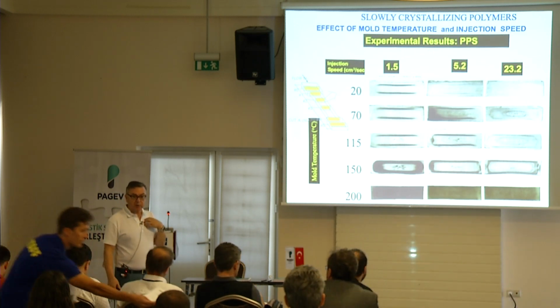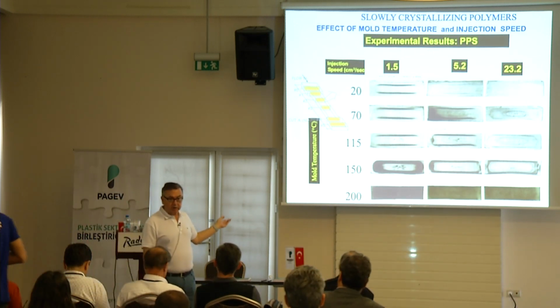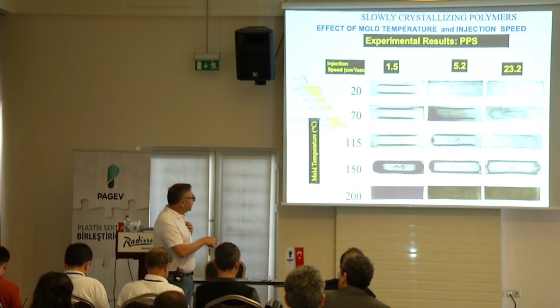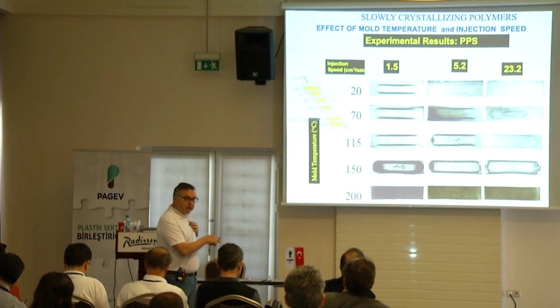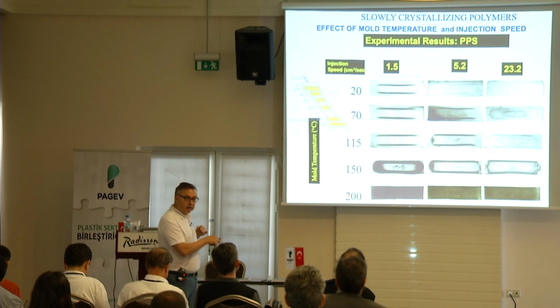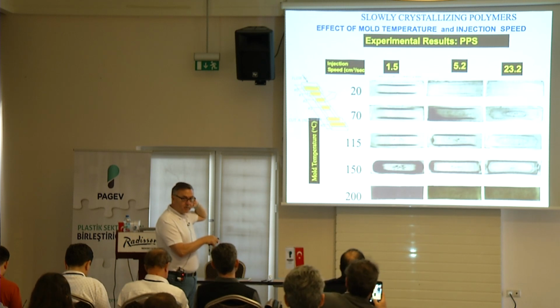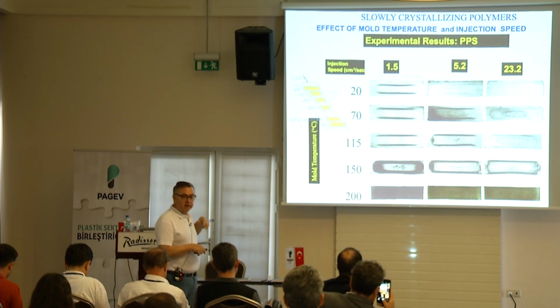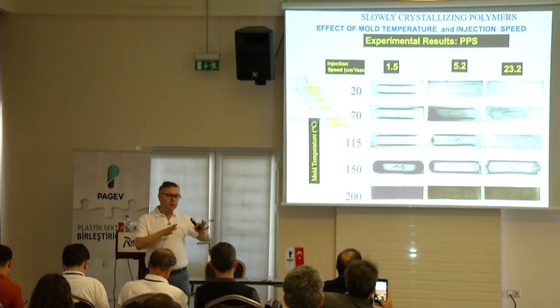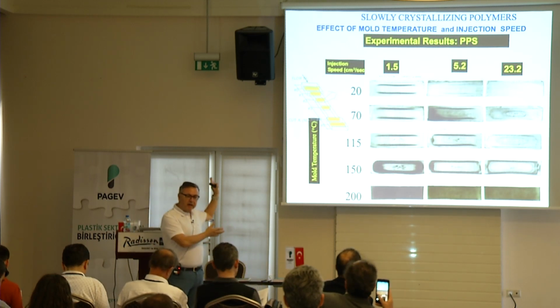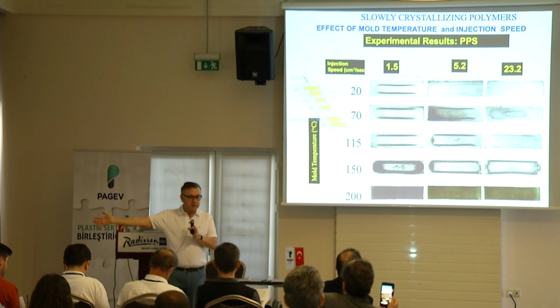So from a heat transfer point of view, if it was a thermal crystallization, the center portion should experience the slowest cooling rates. It should crystallize the most, but it doesn't. It's a dramatically different mechanism. I'm just trying to tell you the difference between the thermal crystallization we've been looking at versus shear crystallization.